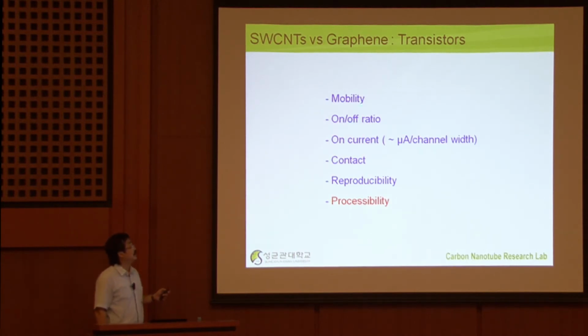So that's one problem. And another real practical problem is on current level, which we don't usually pay attention to, but I'm not going to mention that one. And then another one is this contact. When we use carbon nanotubes for transistor application, we have to connect this guy using some metal layer. And then this metal and semiconducting carbon nanotubes form a Schottky barrier. Somehow, we had a hard time in understanding this phenomenon, even nowadays. So this is actually trouble. And then also, if you make 100 or 1,000 devices, are they working all the same? That is strongly arguable. And again, the processability.